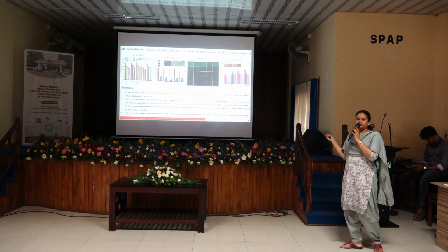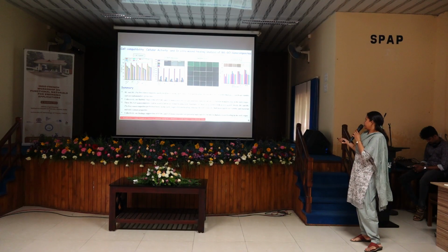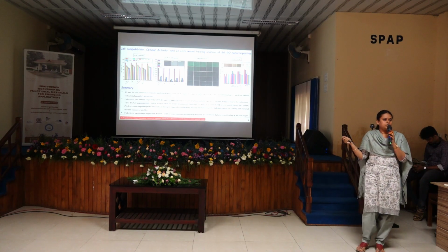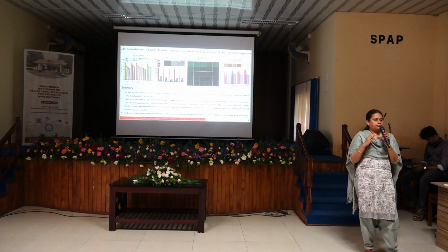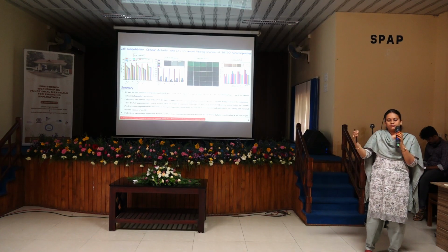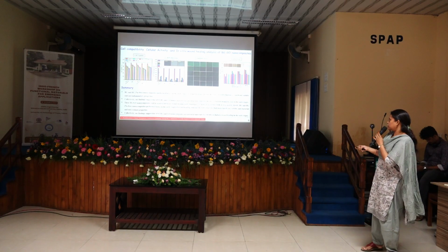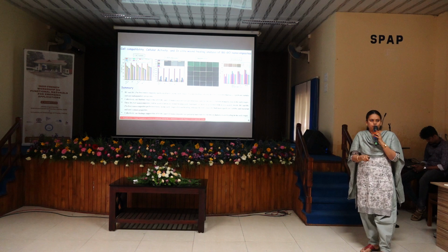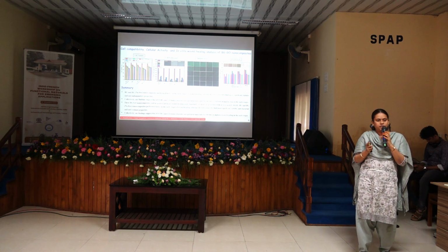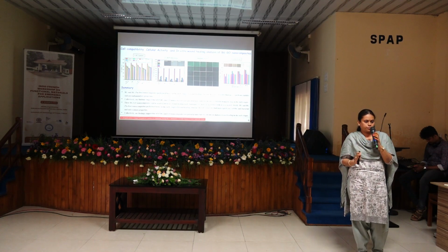Here we have gone for an in vitro scratch assay, but even up to 24 hours we checked, the wound was not completely closed. This is because of the time duration, which we limited to 24 hours due to some technical reasons. So this is how this phase is concluded: incorporating graphene oxide with bioglass gives antibacterial and mild wound closure properties.